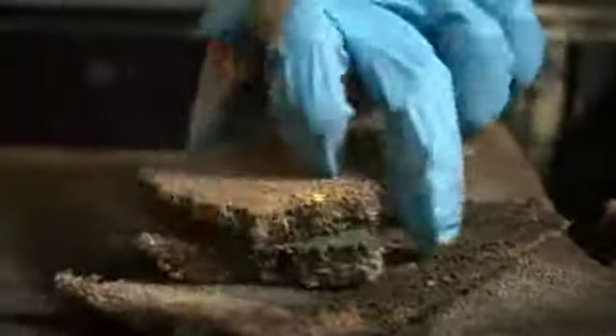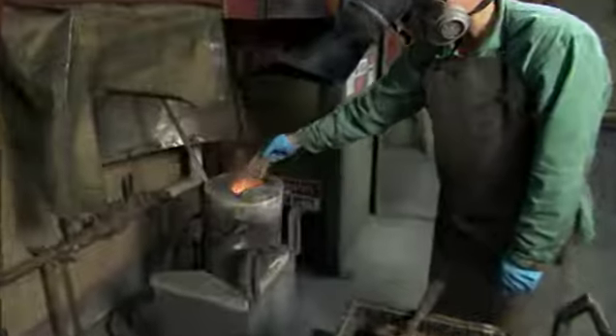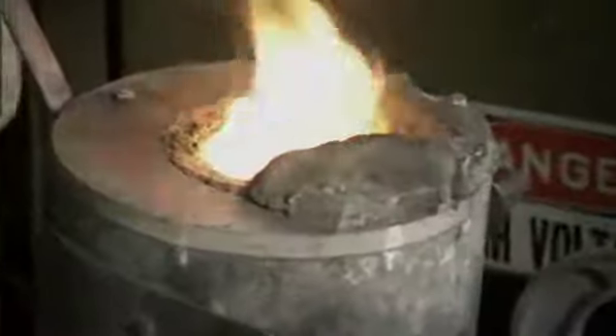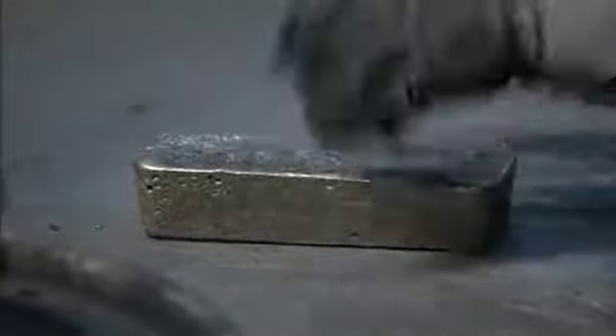That material is cracked into smaller pieces so it will fit into our high-grade melting furnace and slowly instituted into a melt. It takes approximately an hour to get that melt down to a molten metal, at which point we can take a pin sample, which is representative of the homogeneous melt, and then we can pour a bar. After we pour one of these cathode melts, we take the bar. After it's cooled, we clean it and we weigh it, and we perform our assay work so that we could determine an exact amount of gold in one of these bars. These bars usually average 350 to 400 troy ounces of gold.